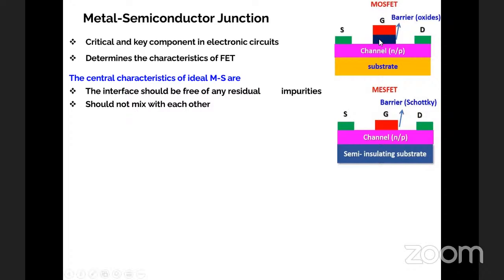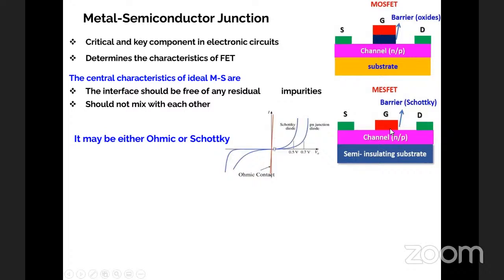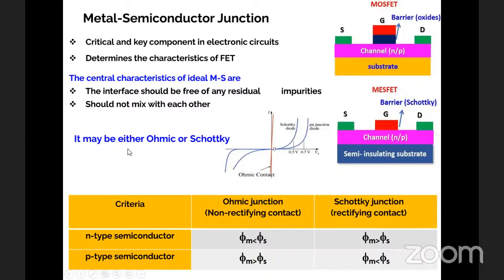But in a metal oxide semiconductor field effect transistor, you need to have a barrier to separate the channel. In a field effect transistor, the gate should always be separated from the channel so that the gate can easily modulate the carriers in the channel material. The channel should usually be a semiconductor that may be either N-type or P-type, that doesn't matter. But in a metal semiconductor field effect transistor, you don't need a barrier oxide, because the Schottky barrier between the metal and semiconductor plays the role of the barrier. When you couple a metal with a semiconductor, it may be either ohmic or Schottky. The important thing is that in electronic devices like MESFETs, the source and the drain must form an ohmic contact with the semiconductor channel, while the gate should form a Schottky barrier.